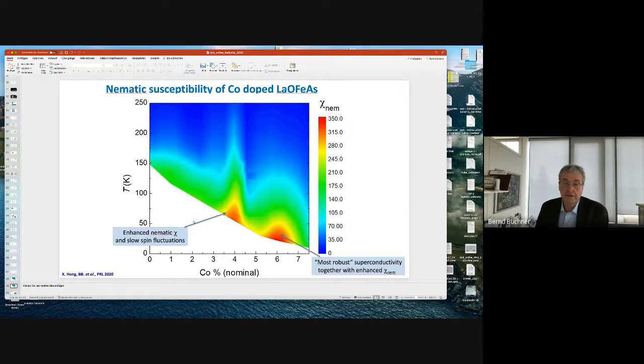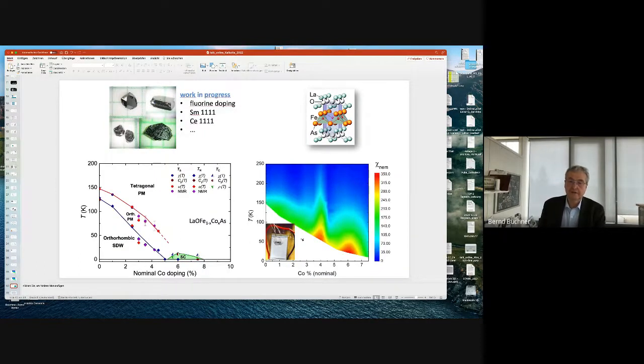And one is connected to the concentration where the magnetic order disappears. So in some sense, what you see here is the coupling between this electronic instability and the spin degrees of freedom, which we of course expect, since this magnetic order is of stripe-like nature and also breaks this C4 symmetry. The biggest surprise is that we have a second region here, which is very, very similar to our superconducting dome. So it looks a little bit like this region is mimicking the superconducting dome that we really have, and I think this statement is a robust statement.